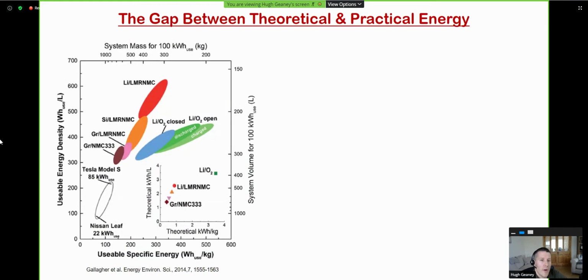So in terms of the gap then between theoretical and practical energy density, this is a really nice paper that looked at the modeling of a system size for a given specific energy. So what we would have seen, and I didn't give the numbers, is things like the lithium-air system. You'll very often read a paper where the theoretical energy density is comparable to gasoline. It's actually shown here. So it could be 4 times higher than the current state of the art. But when people actually start to calculate out the system that you would really need, you'll see that the improvements are actually far more modest.